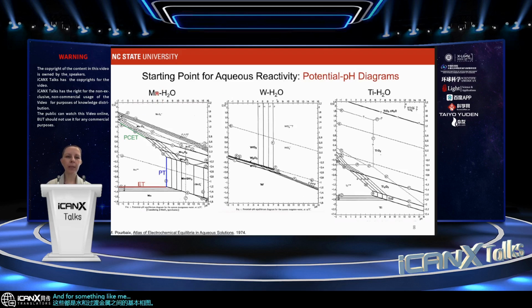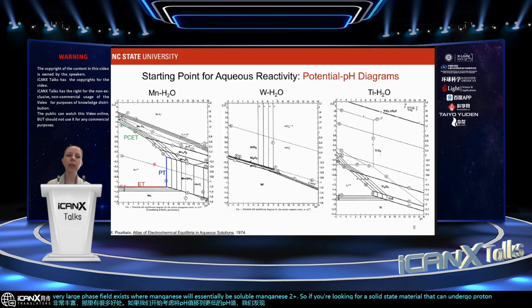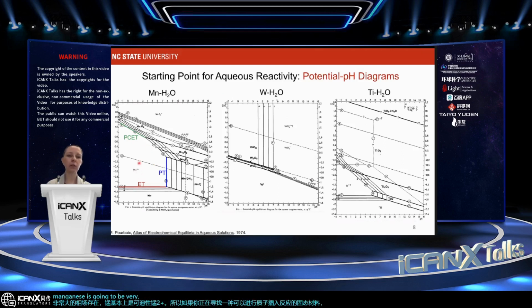And for something like manganese, which is a very interesting transition metal utilized in alkaline batteries, so alkaline aqueous electrolyte batteries working at high pH over here, very abundant, a lot of benefits there. If we start to think about shifting to lower pHs, we find that this very large phase field exists where manganese will essentially be soluble manganese 2+. So if you're looking for a solid state material that can undergo proton insertion reactions, manganese is going to be very, very difficult to stabilize from a thermodynamic standpoint.